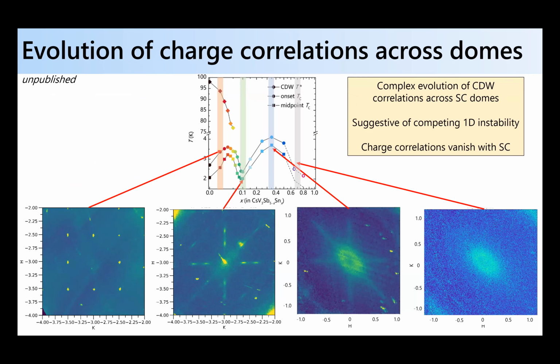And we can actually keep doping, and we can look out here at the peak of the second dome, and out here it even gets weirder, because here you still have broken translational symmetry, you have an incommensurate q. But here, you basically restore translational symmetry, but you still have these quasi-one-dimensional domains. So rotational symmetry is broken here, but it seems like translational symmetry is restored. So you might call this a nematic phase, potentially. And then if you keep going out here, where superconductivity dies, then all the charge correlations are gone within the resolution of our current measurement.